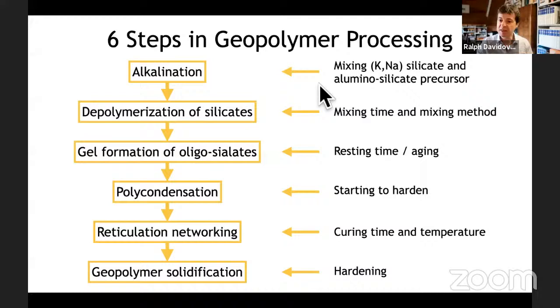And because you understand now the real process, you know what to do to solve any problem occurring during the reaction. If there's something wrong in the mixing time and mixing method, you will have a bad depolymerization of silicates. If you don't use the right curing time and curing temperature, the network will be weak, and so on and so on. So you understand what is happening and you know where to act to solve this problem or to improve your properties.